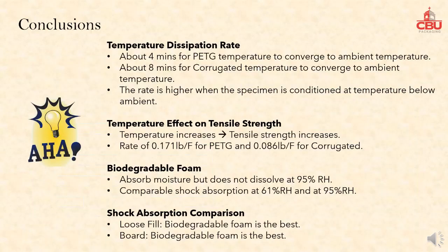The following conclusions can be made from this study. 1. Temperature dissipation rate for PETG is much faster than that of corrugated. 2. As temperature rises, the tensile strength rises in both PETG and corrugated. But the increase rate of PETG is higher than that of corrugated. 3. Biodegradable foam does not dissolve at 95% relative humidity. It also gives the best shock absorption.